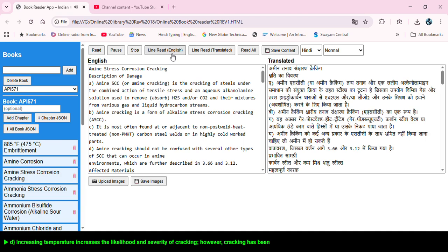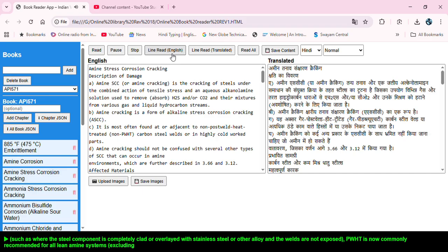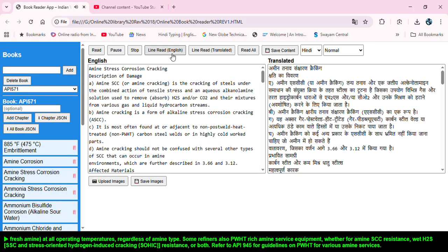D. Increasing temperature increases the likelihood and severity of cracking. However, cracking has been reported down to ambient temperatures with some amines, MEA in particular, other than in special cases, such as where the steel component is completely clad or overlaid with stainless steel or other alloy and the welds are not exposed. PWHT is now commonly recommended for all lean amine systems, excluding fresh amine, at all operating temperatures,